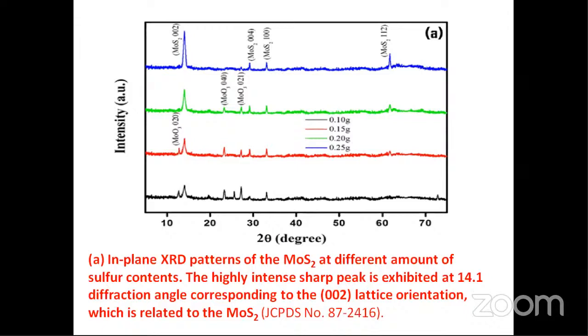then we found very high crystalline, good quality MoS2 peaks. This is along the C axis, that is the 002 lattice orientation. This is called the C axis orientation. That is very good for the stacking layer structures, and this is good for our electronic devices and other things.